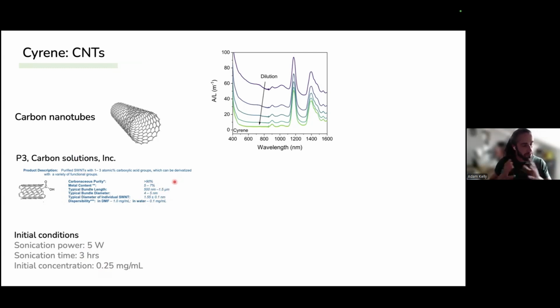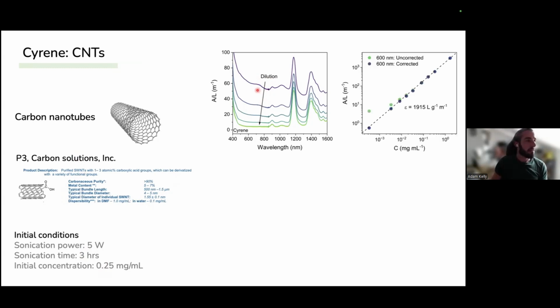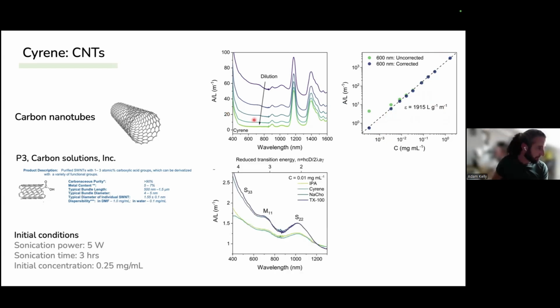Because the masses you work with are typically quite low, we wanted to produce a dilution series. So we started with a very concentrated, known concentration of carbon nanotubes and diluted it down to get UV-vis spectra. Then by plotting the value at 660 nanometers, or 600 nanometers, I should say, against concentration, we're able to extract an extinction coefficient, which means regardless of how low the concentration is, we can use UV-vis to determine the concentration of our material.